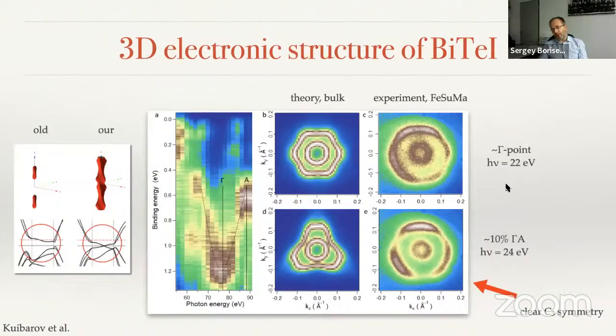But the intensity distribution, of course, is a little bit unusual, and there are many more features. And the geometry, because here you need to rotate the sample. In this case, we rotated the sample, constantly changing the geometry. So we decided to apply our FeSuMa in order to clarify whether this is the case. And indeed, we took the data at 2 energies. We did a short scan, actually rather long scan on the photon energies. We saw the 3D dispersion, which tells us that we are sensitive to the bulk with conventional energies from 50 to 90.